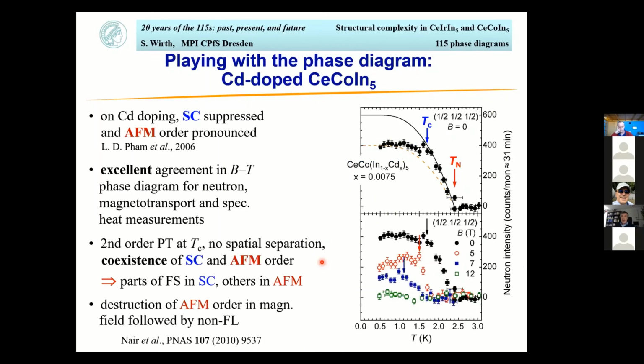But the point actually I want to make is here these nice neutron scattering data. As you cool down here for this particular sample, as you go below the Néel temperature here, then you see the expected rise of the neutron intensity, and you can actually fit that by a Brillouin function very nicely here. But then as you go to TC, just below TC, it just stays put here. Typically, you would expect the intensity to go down again. And that's actually true for a number of fields here as shown here, but it's best seen in zero field.